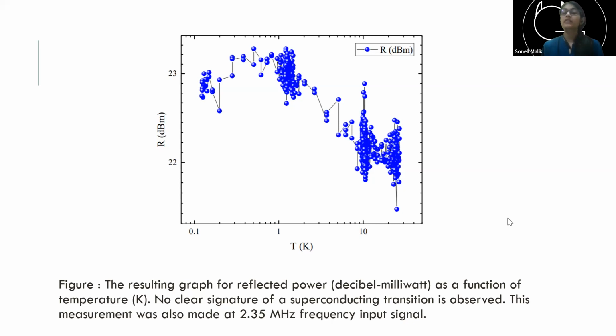Because you can't send a lot of wires into your dilution fridge. The dilution fridge goes to temperatures as low as 10 millikelvin. Now, if I have 20 wires going into my dilution fridge, and copper in itself is a very good thermal conductor, then with all those wires it will take me much longer to cool down my system to the temperatures that I am hoping to reach. So there are very limited numbers of probes. And because, like I mentioned, it will take a whole cycle of 8 to 9 days to measure one batch of samples,